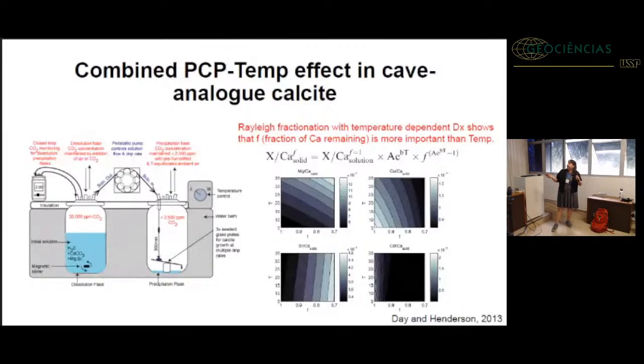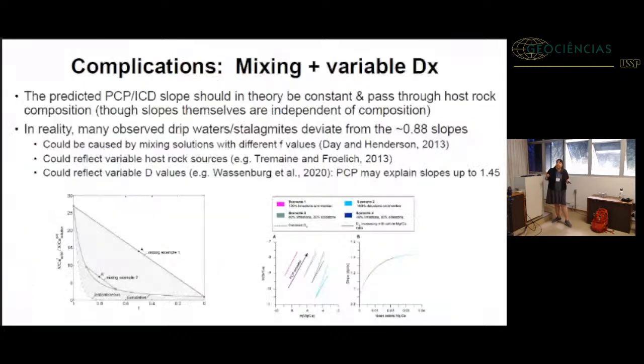If temperature was the main effect, you would expect these contours to be pretty much vertical, but they're not here for magnesium calcium. So they basically conclude that changes in solution composition are likely more important than temperature. Another really interesting finding from Day and Henderson over here is about mixing. We talked about mixing, somebody talked about mixing lines yesterday. That was JP, I believe.